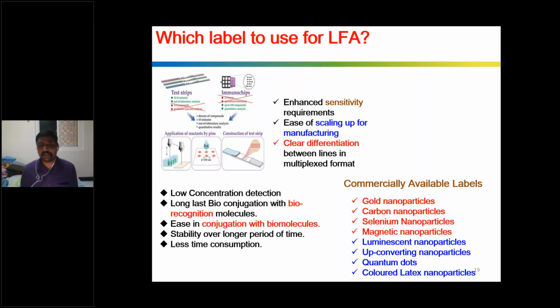So nowadays we are using the gold nanoparticle. It can be stable for another 2 to 3 years. And then the most important one is less time consumption. When you do the test, the result should come in less than 10 minutes or 15 minutes, not more than that. So these are the important points when you consider lateral flow analysis and the labeling material.